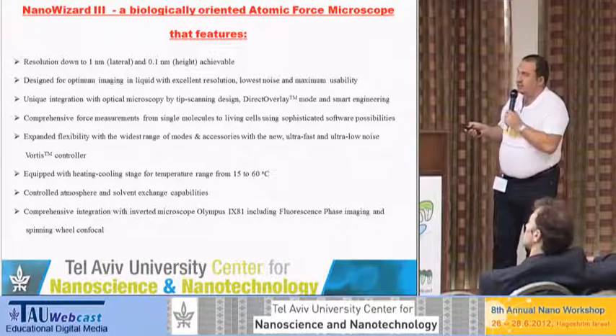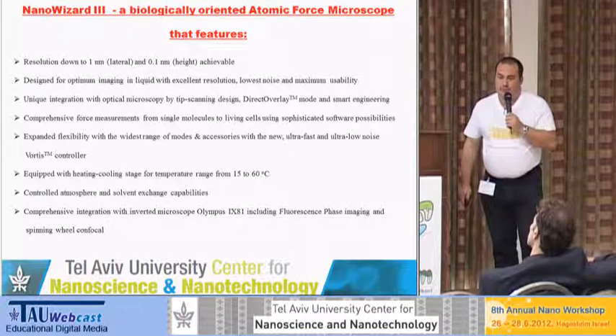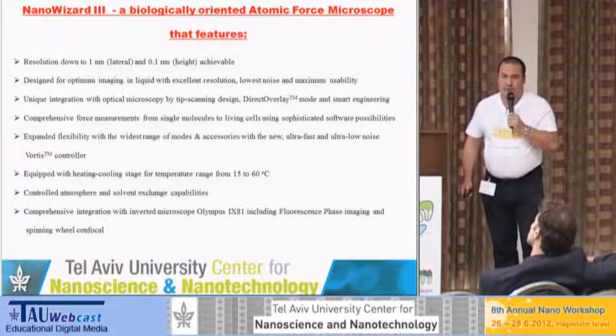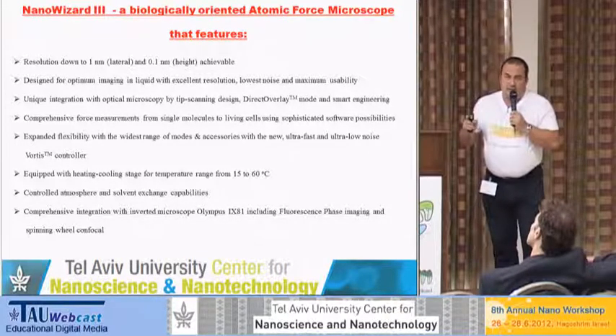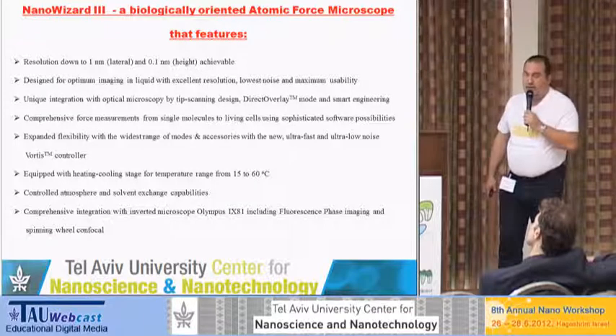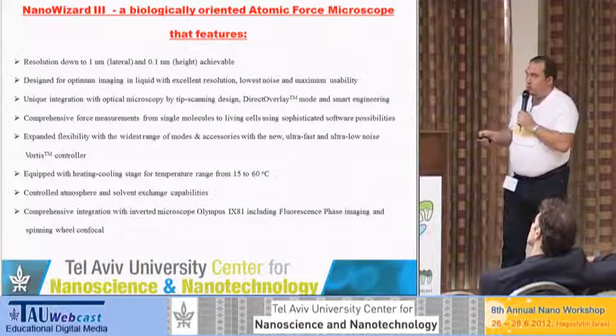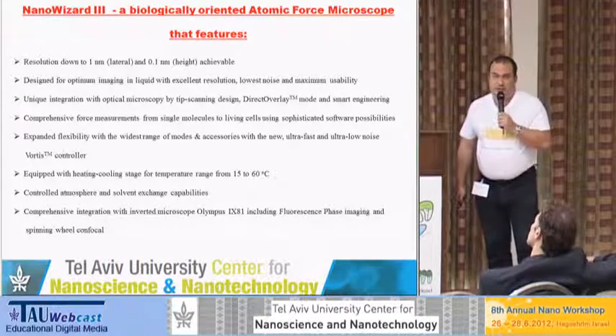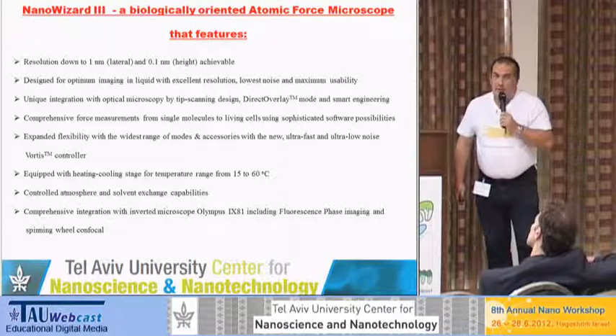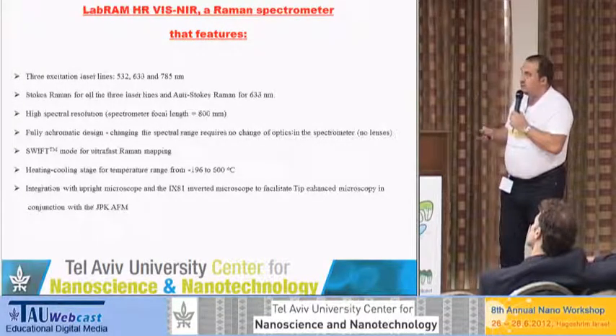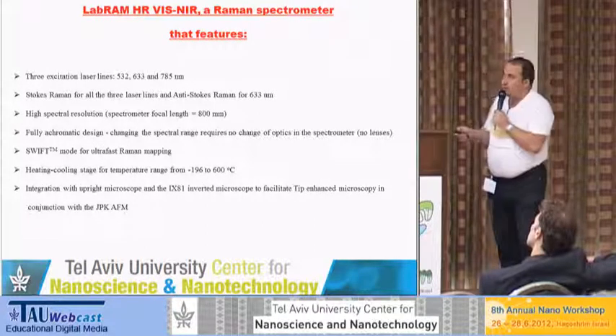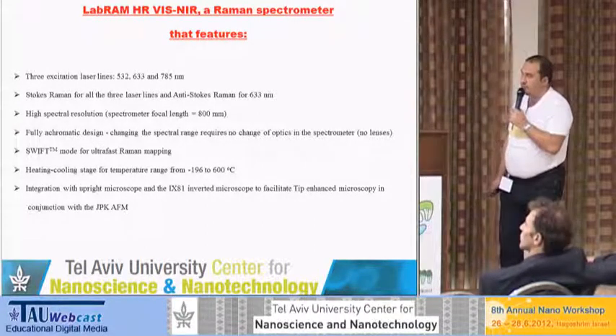For example, it also has the direct overlay feature, which allows you to import the optical image, bright field or fluorescent image, into the AFM and to correlate it with the tip position and to directly move the tip to the desired area and take AFM scan there or probe the mechanical properties. And it is also equipped with a stage with the temperature control from 15 to 60 degrees centigrade, which actually covers all the range required for biological samples.